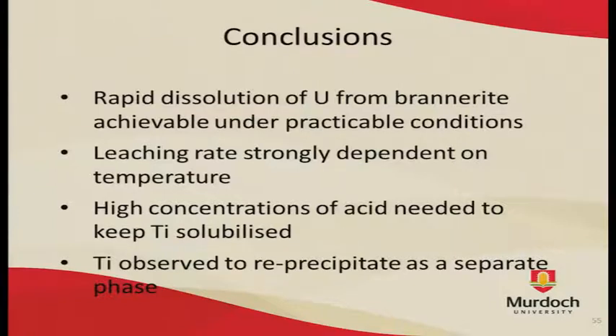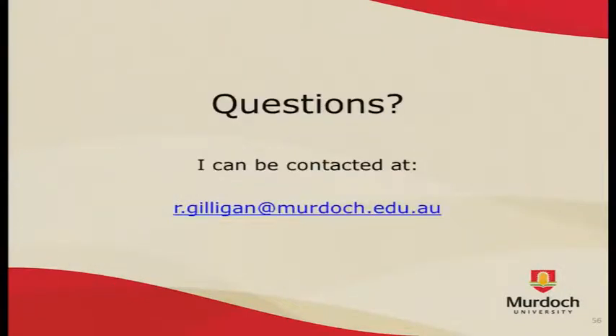Increasing the concentration of acid prevents the reprecipitation of titanium and has a slight positive effect on uranium extraction. A high free acid concentration seems to be needed in order to break apart the titanium lattice and get the uranium out into solution. So, yeah. Any questions?